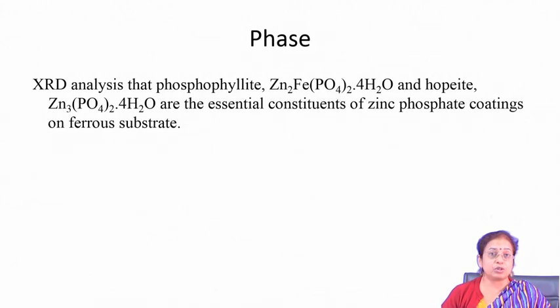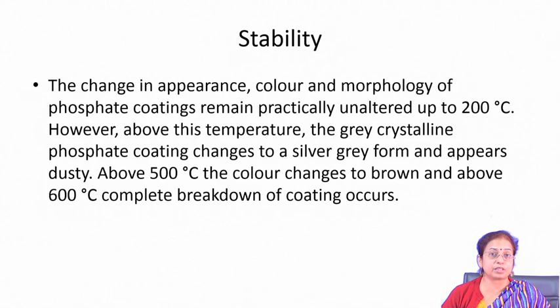this is also good to reduce the coefficient of friction to a large extent. Usually it is observed that when you do coefficient of friction measurement, it is much lower in phosphated surface as compared to that of unphosphated surface.